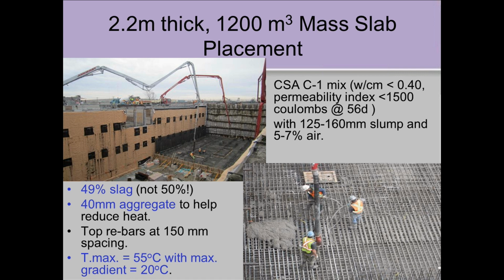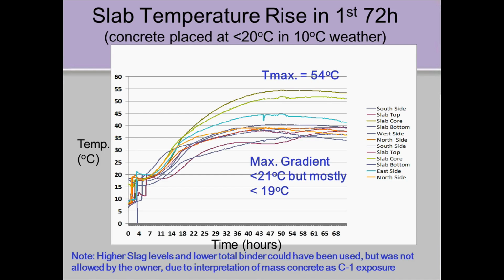I've got 2 slides. So we actually did one of these pours at a station. They had 3 pumps going. They're pumping it to 2.2 meters thick using large aggregate. They did a number of things. They controlled their temperature. They were getting the low permeability, and actually monitored this large pour. It was 1,200 cubic meters. They got to 54, so they just made it on the 55, and the gradient was generally less than 20, with one exception in one corner.